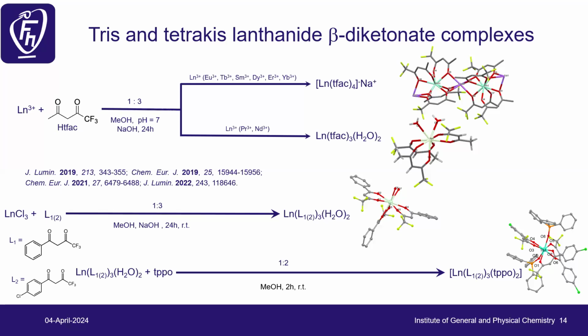are larger ionic radius. So here we have tetrakis complexes where sodium is a counter ion, but also a bridging ion. And for the praseodymium and neodymium, we got tris complexes. When we increase the ratio between lanthanide and beta-diketonate to 1:4, we also obtain the tetrakis complexes.